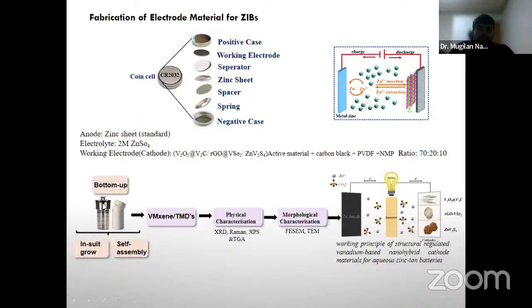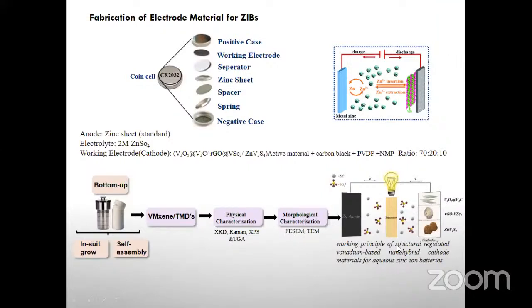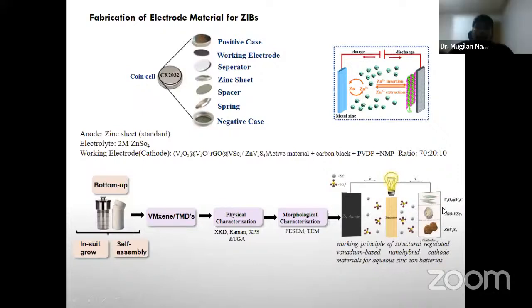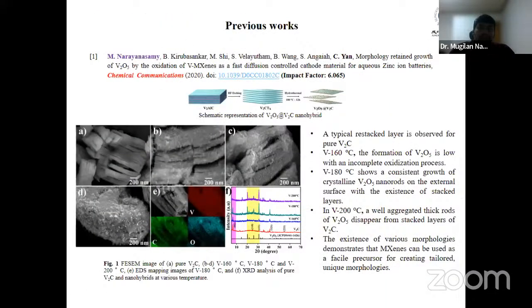We will be doing this with the hydrothermal or solvothermal method. With in situ growth or self-assembly, we will prepare the electrode material. For physical characterization, we'll go with XRD, Raman, XPS, and TGA. Morphological characterizations like FESEM and TEM. And finally, we will be studying the electrochemical property of the material we prepared, like hybrids of oxides and carbides, or graphene oxide hybrid with selenium. Here I have two of my previously published works to discuss shortly.